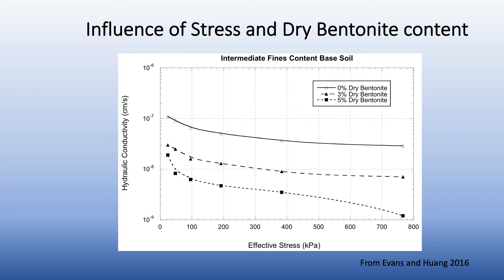Not all materials are as stress-dependent as the Birdsboro site. For an intermediate fine soil, the decrease in hydraulic conductivity over the stress range tested is about half to one order of magnitude, depending upon the dry bentonite content.